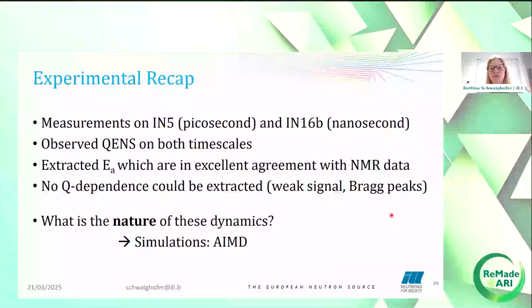So just to give a brief recap of our experimental data, we have data from IN5 on a picosecond timescale and IN16B on a nanosecond timescale. They agree well with NMR data, but due to the weak signal and the many Bragg peaks, we were not able to investigate the Q dependence. Therefore, we don't know yet from the experimental data what the nature of our dynamics is. To overcome this problem, we moved to ab initio molecular dynamics simulations.